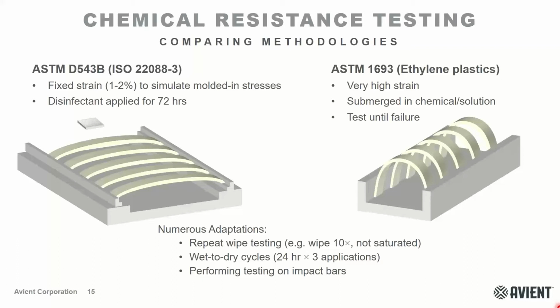This test isn't really designed for all materials, especially a lot of those going into the healthcare industry, which are oftentimes engineering resins. So the ASTM D543 method is also commonly used for looking at chemical resistance and environmental stress cracking resistance in particular. This method takes tensile bars and potentially flex bars as well, and puts them into a strain jig that has a fixed strain of 1 to 2%, which is meant to simulate molded-in stresses.